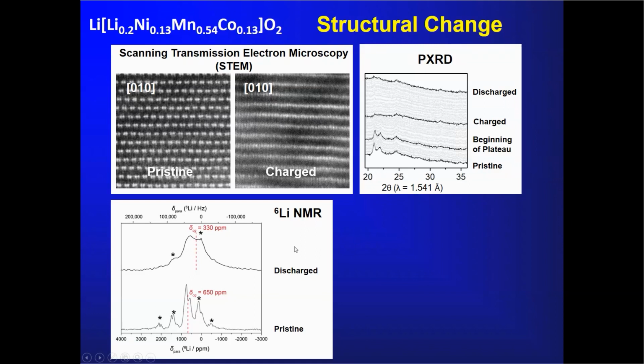And these other two pieces of evidence here simply support that. You see this is the powder diffraction pattern, the superstructure peaks, and you see the disappearance of these superstructure peaks on charge, and they never truly reappear on discharge. So it's an irreversible process.